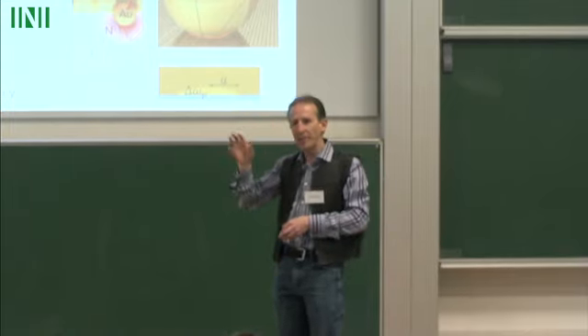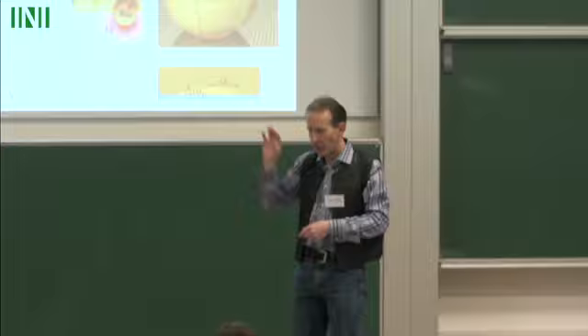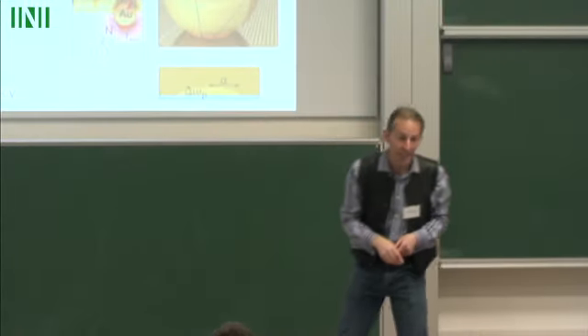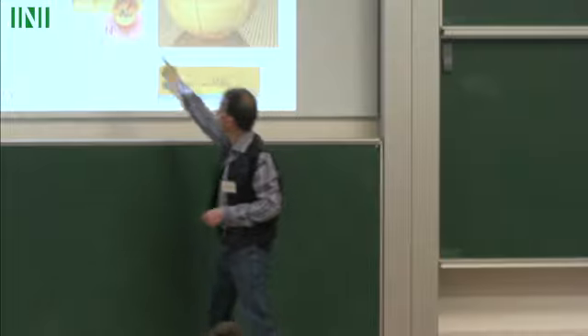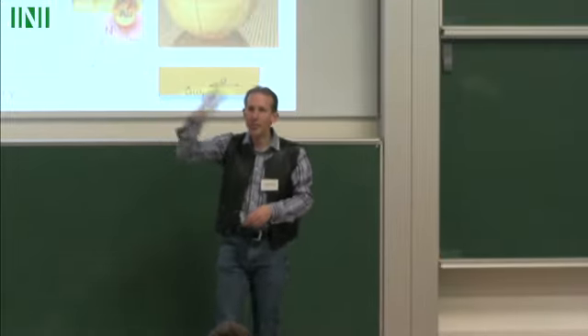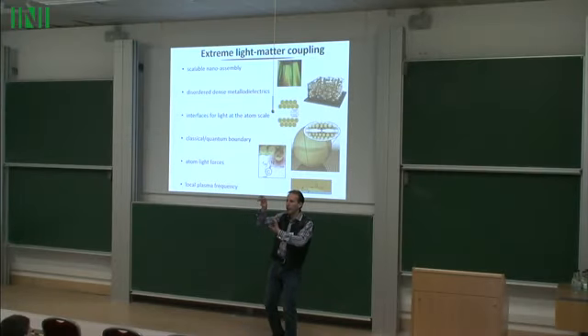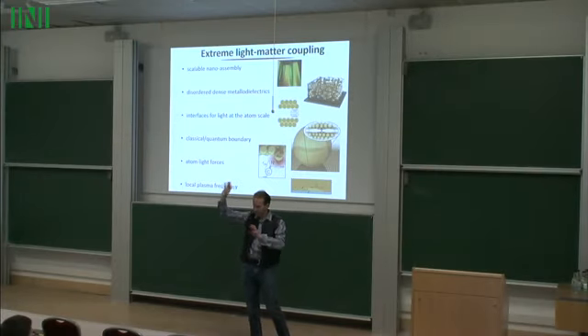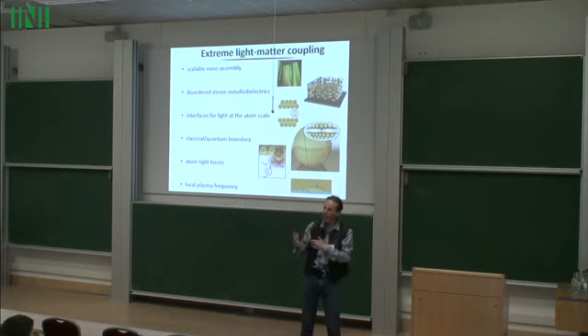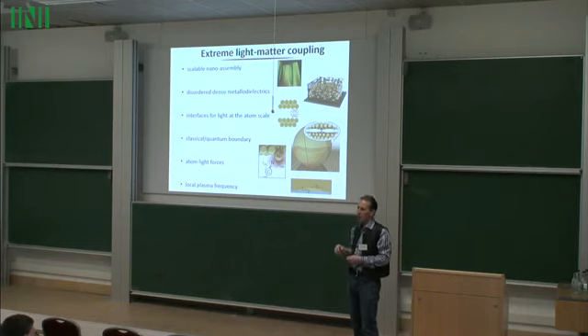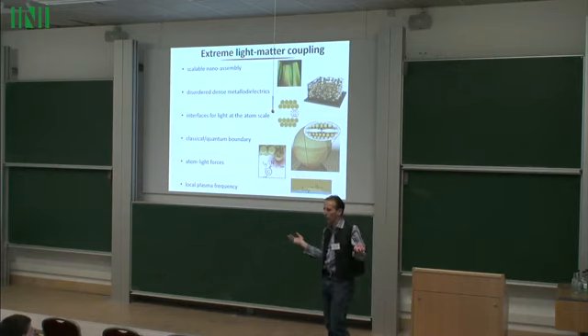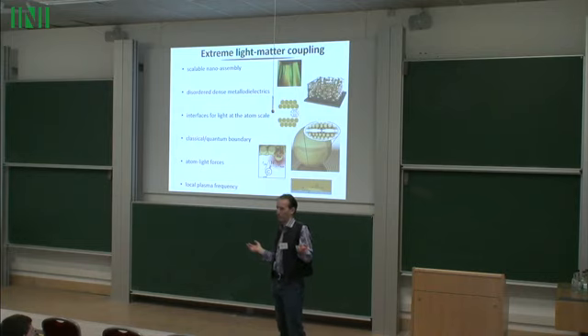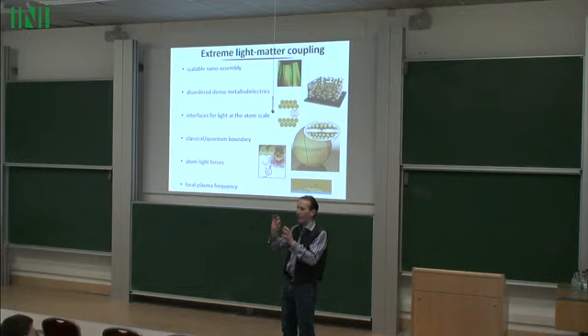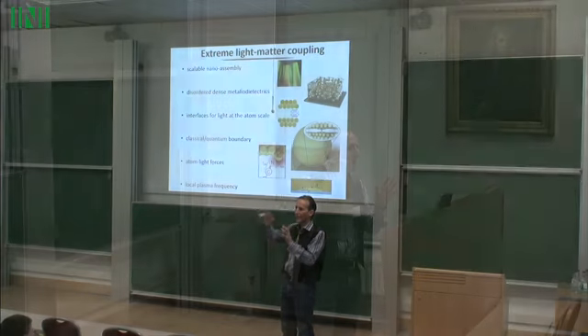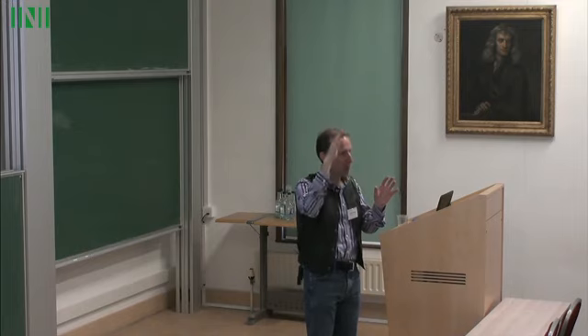One of the interesting things is that this gold atom that gets pulled down, it really literally gets pulled down. It's the light that forces this gold atom down. We can then reduce the light level and it'll be stable there, and then when we increase the light we can push it back in again. That's why we know the forces exist, we know the sort of energy scales, but we don't know how it happens. We have an idea of gold as a solid at room temperature, but that's the wrong model. It's solid in the bulk, but the surface atoms are more like soup. They can move around easily, and particularly when you have light on them, they can really move around easily.